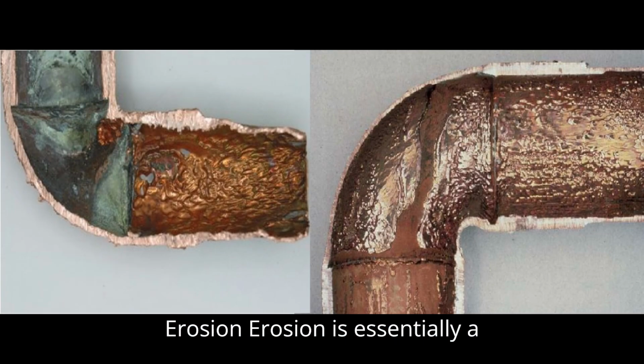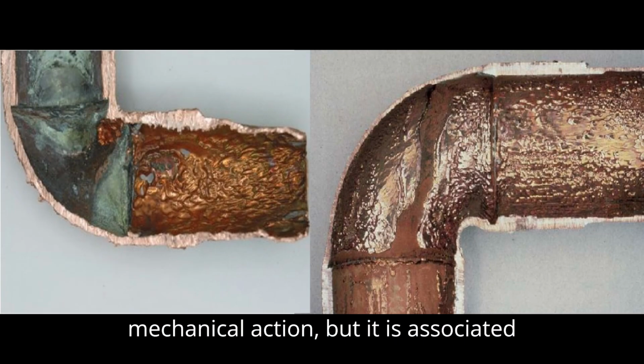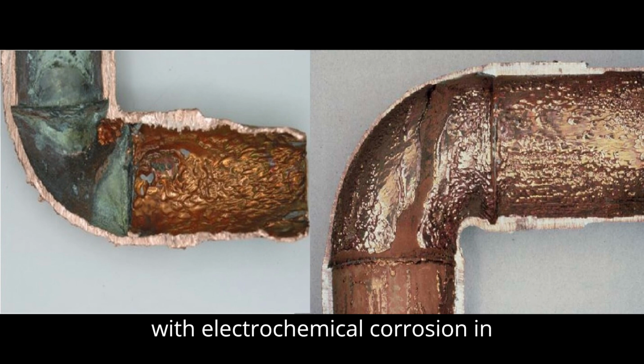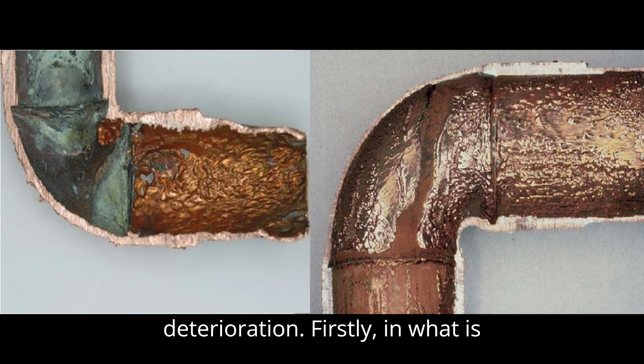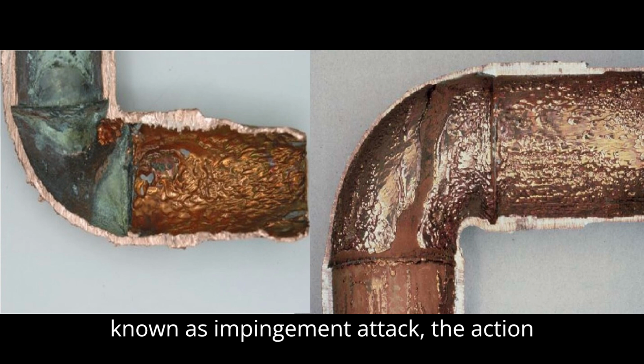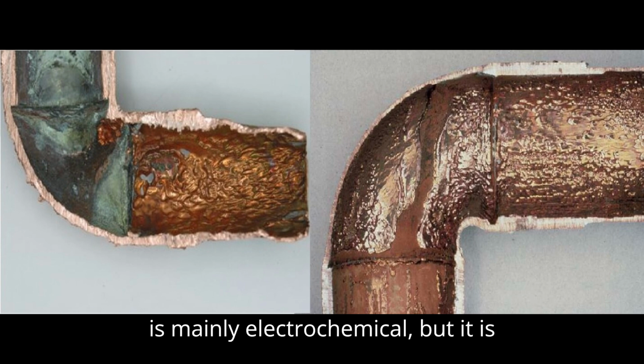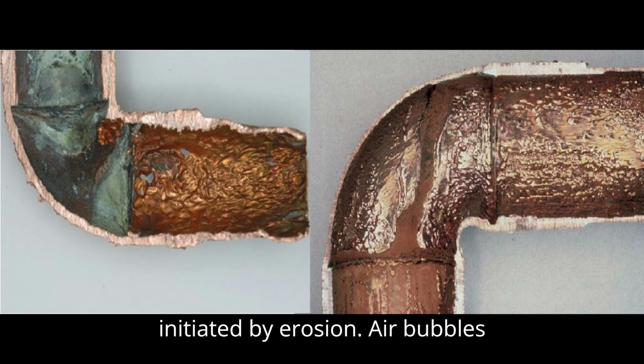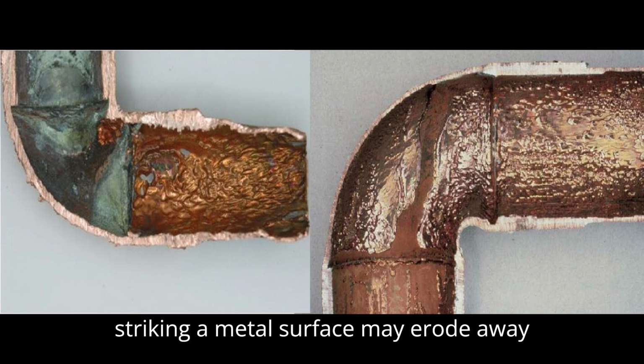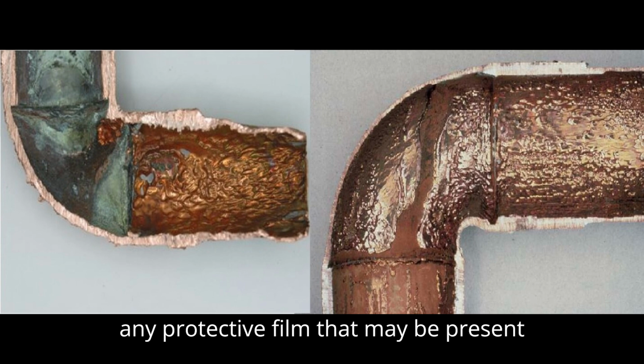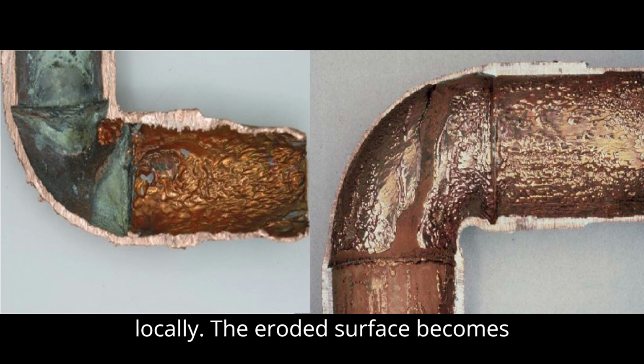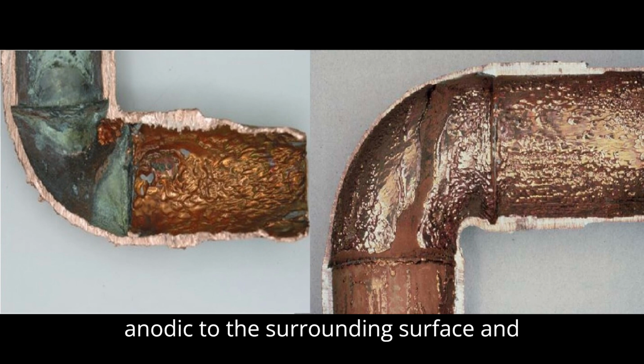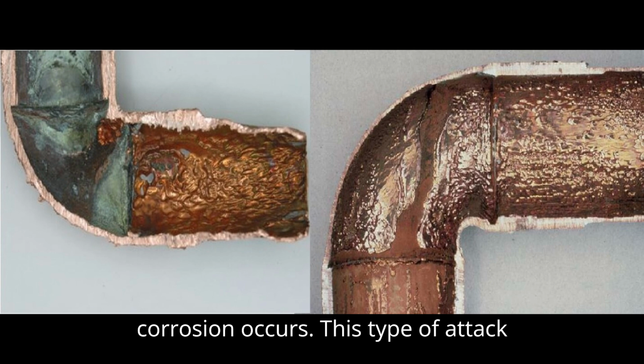Erosion. Erosion is essentially a mechanical action, but it is associated with electrochemical corrosion in producing two forms of metal deterioration. Firstly, in what is known as impingement attack, the action is mainly electrochemical, but it is initiated by erosion. Air bubbles entrained in the flow of water and striking a metal surface may erode away any protective film that may be present locally. The eroded surface becomes anodic to the surrounding surface and corrosion occurs.